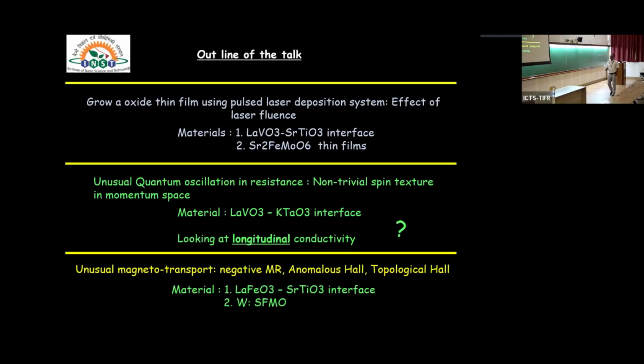Okay. So this is the outline of the talk. We're first going to talk about growing of oxide film using pulse laser deposition system, which DD has already given a nice introduction about, and how these interfaces and materials could possibly become conducting. We're going to talk about two materials, and the effect of the laser fluence on your target and how it changes the behavior of the material. First system is the lanthanum vanadate, strontium titanate interface. Second is the strontium iron molybdenum oxide, double perovskite thin film.